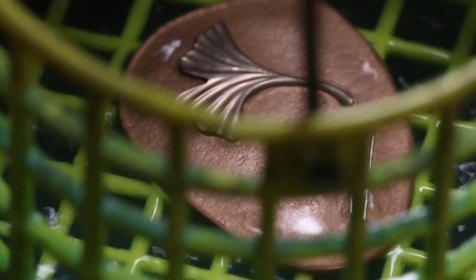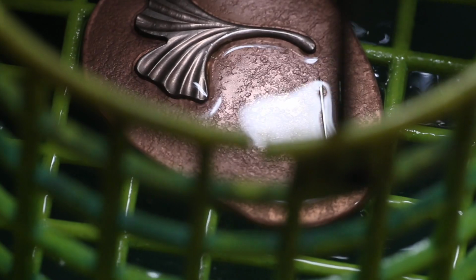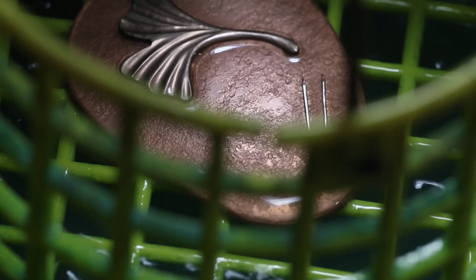Right, so I've got a patina developing now. I don't know if you can see. It's developing an opaque color, but I can still see through the layer. It's not quite fully opaque yet. You see? I don't want to leave it out of the liquid for too long. Okay. And you might discern that subtle iridescence on the surface. At this point, I'm not worried about that because we're still building up an opaque layer. By opaque, I mean a layer that you can't see through. It's a true solid color on the surface of the metal.